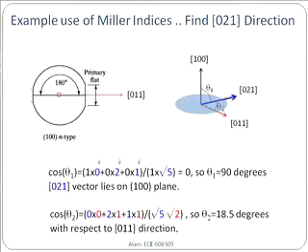Now in this case, we were lucky that the vector turned out to be in the same plane as 021. If the angle was, let's say, 85 degrees or 120 degrees, then you would have to saw the wafer at an angle to define that 120 degrees and then rotate it along. And so therefore, at the end, you will determine that 021 is at 18 degrees with respect to the primary flat, and you will create your wafer or your device there, shown here in the blue patch, and your advisor will be very happy.